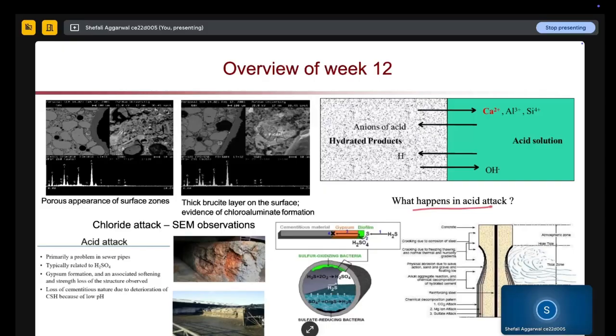So here, if you see in pictorial form what is happening in acid attack, all the positive ions like calcium, aluminum, silicon from your concrete system will move towards the acid solution, and all your negative ions will move towards your hydrated products. So all the CSH hydrated products will get deteriorated and will move away from the concrete system. This will cause loosening of the strength of your concrete system, and in turn will cause the deterioration of your concrete system. So this is another example showing in a sewer pipe how sulfuric acid is forming and how it is reacting with your cementitious material and causing the deterioration of your concrete system.